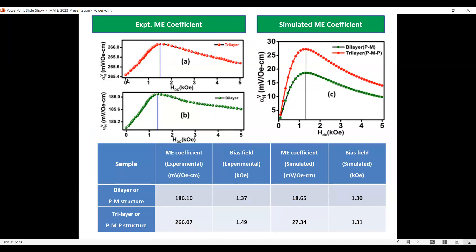In the range of increasing magnetic field from 0 to 5 kOe, there is an increase in the ME coefficient up to a certain optimum magnetic field, followed by a decrease in a nonlinear fashion. Both the bilayer and trilayer show the same type of alpha variation with respect to the magnetic field. This is because as we increase the magnetic field, there is a generation of piezomagnetic strain, but after the optimum field, the magnetostriction saturates in the piezomagnetic phase, which reduces the stress transfer and causes a decrease of alpha with respect to H_DC. The simulated ME coefficients follow the same nature for both bilayer and trilayer structures.